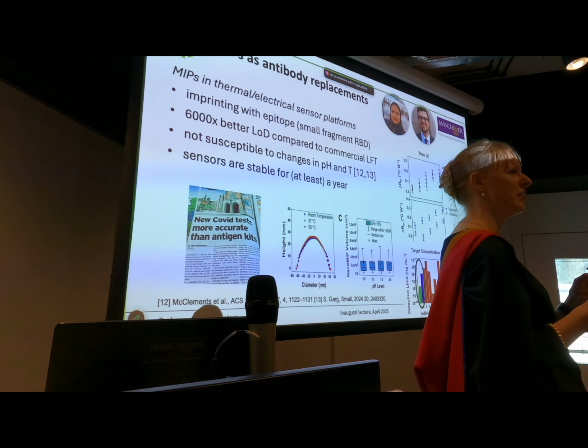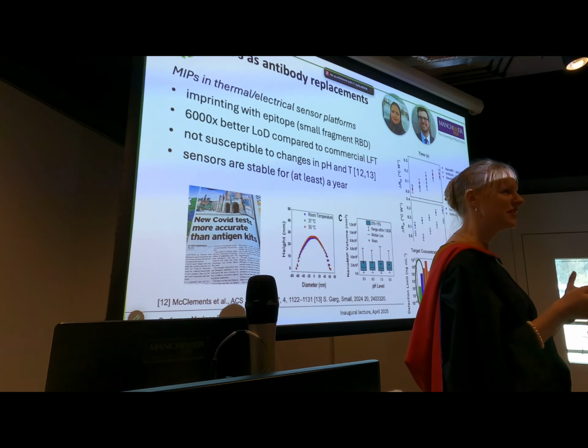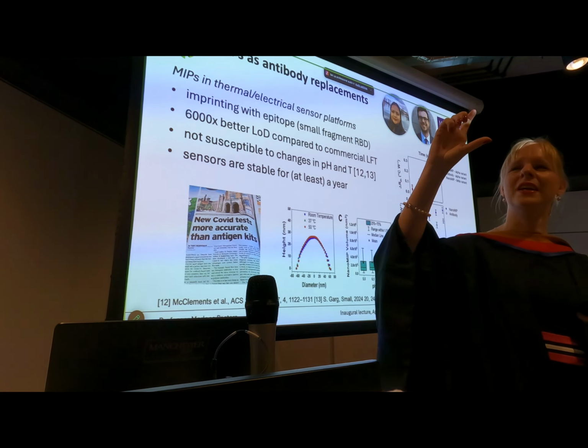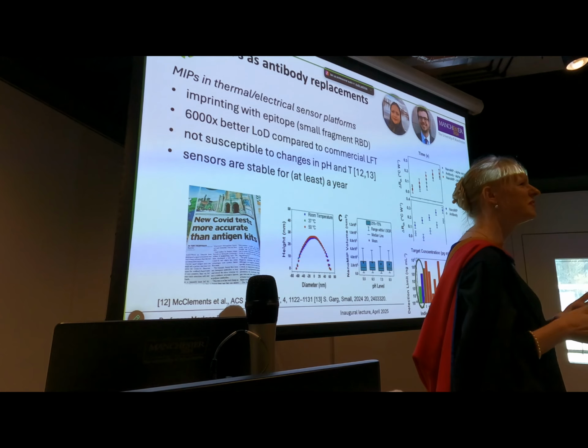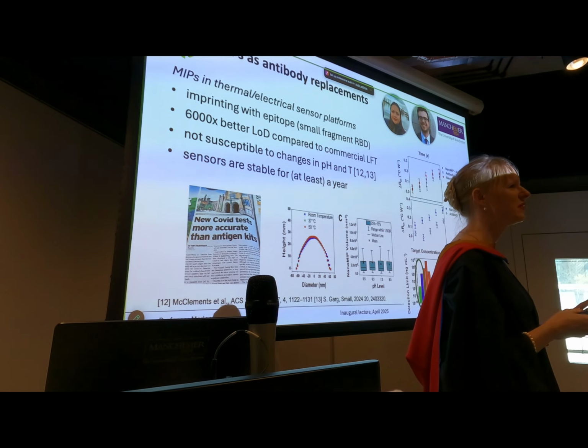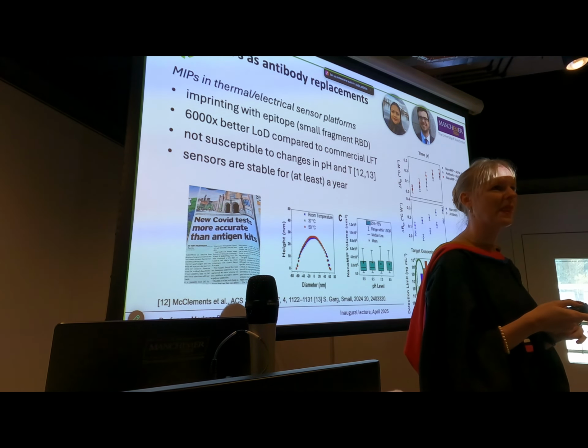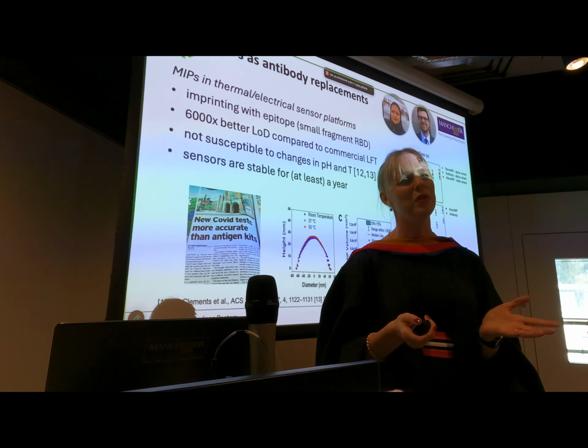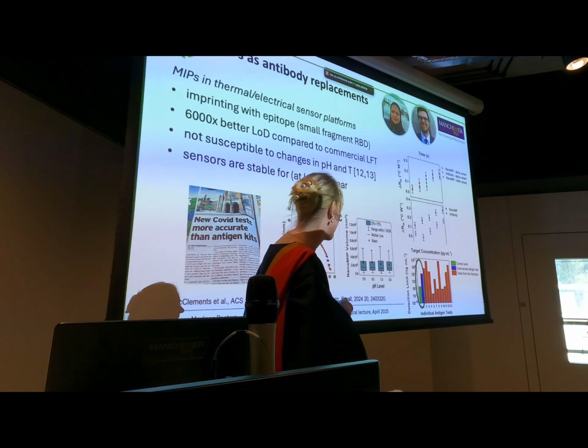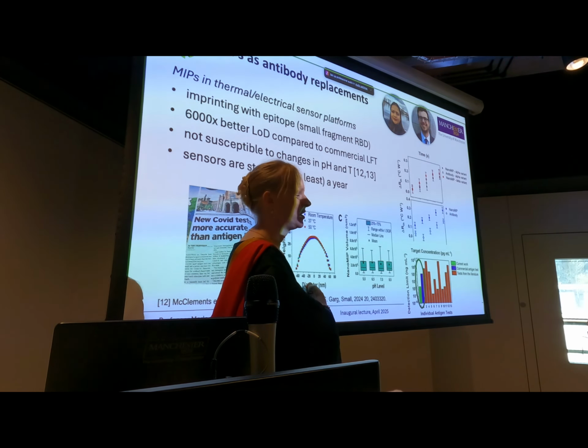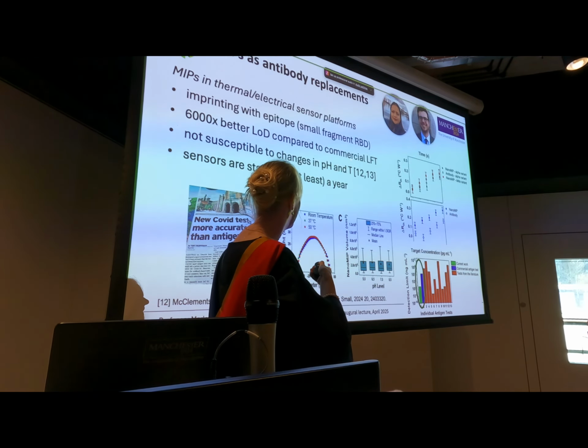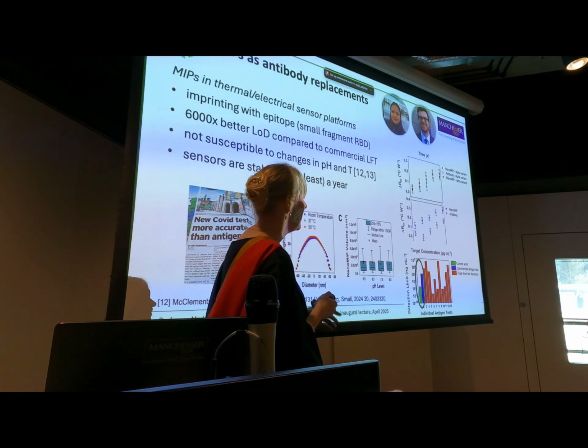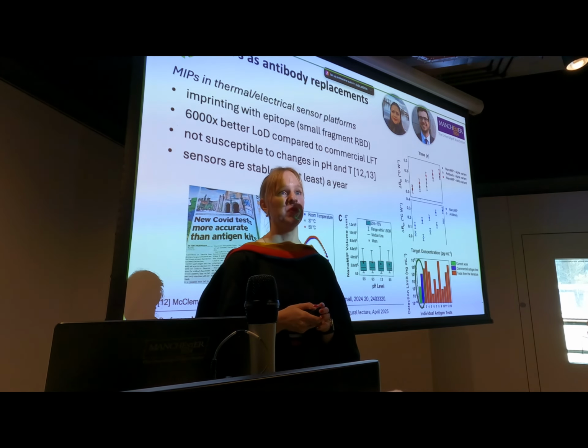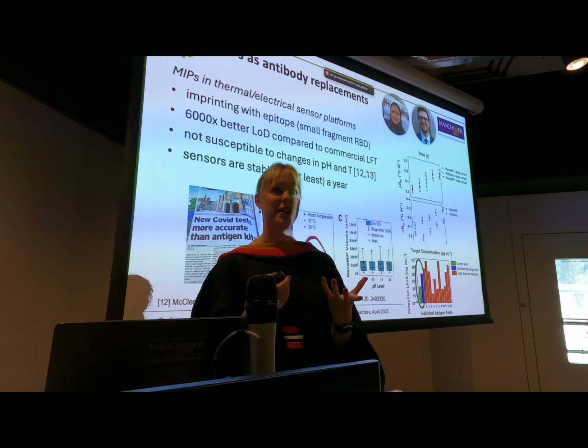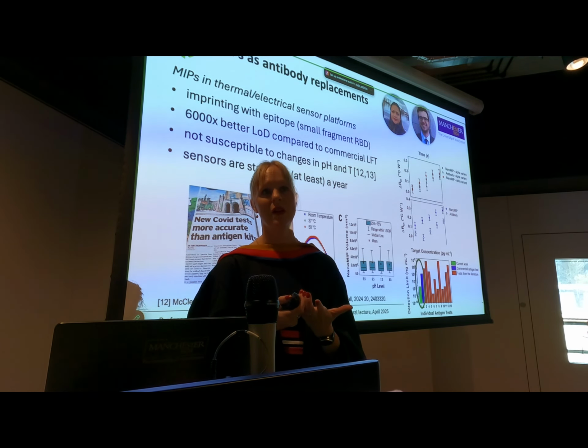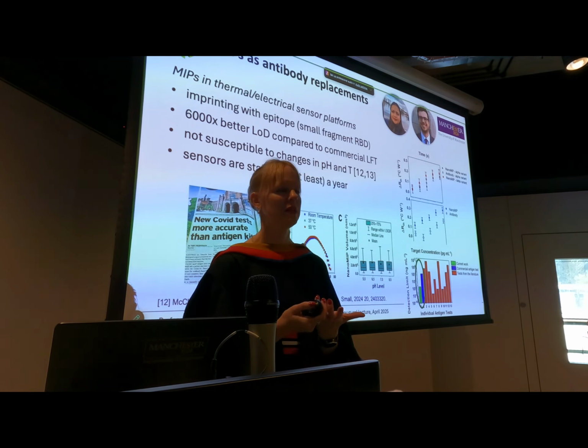And people also compare it to lines, which you might get for a pregnancy test, but also for the COVID lateral flow test, it was like, is this positive? Is this not positive? It doesn't really give you a very definitive answer sometimes. So luckily, we can do this with our sensor platform. And at the time, we obviously published this also in the newspaper, and it was saying that we can get up to 6,000 times better in terms of the limit of detection compared to a lateral flow test.